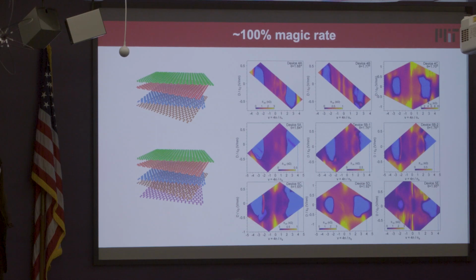Yeah, that's a very good question. The way at least our lab assigns the density is not just through the map of the features. We do it through the quantum oscillation Landau fans, to make sure that that point is actually where the carriers emerge. That's how we assign it in the first place.